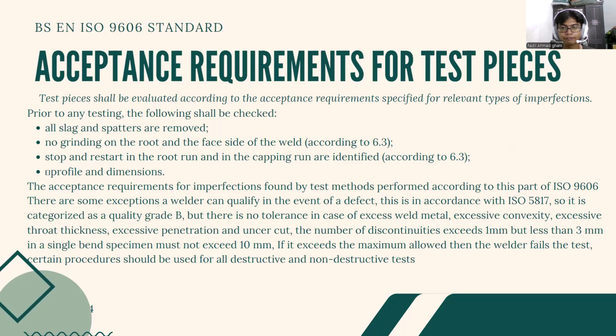A welder can qualify in the event of a defect. This is in accordance with ISO 5817, so it is a category qualified as grade B. But there is no tolerance in case of excess weld metal, excessive convexity, excessive throat thickness, excessive penetration, and undercut. The number of these imperfections that exceed 1 millimeter but are less than 3 millimeter on all bend specimens must not exceed 10 millimeter. If it exceeds the maximum allowed, then the welder fails the test.